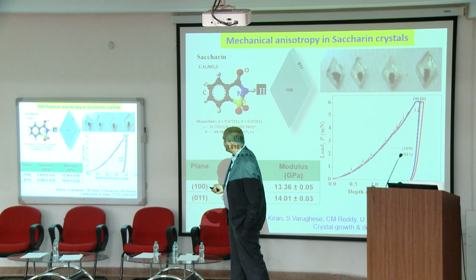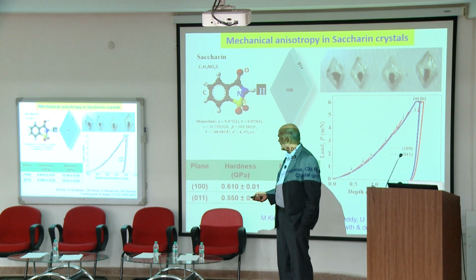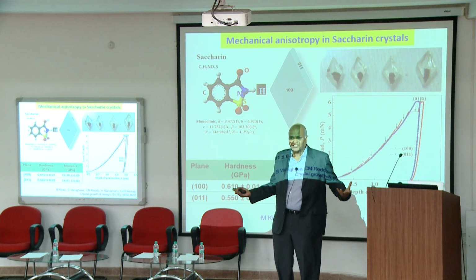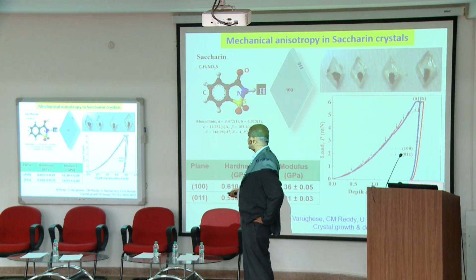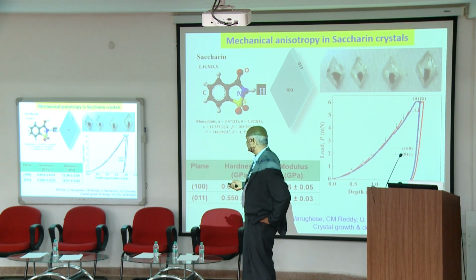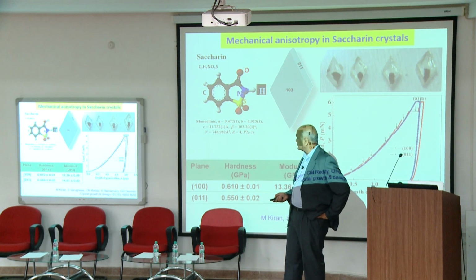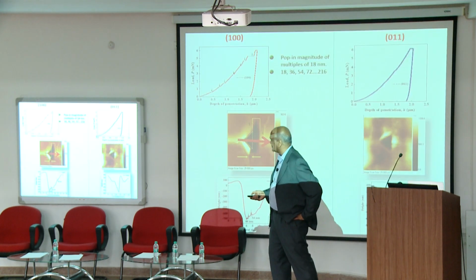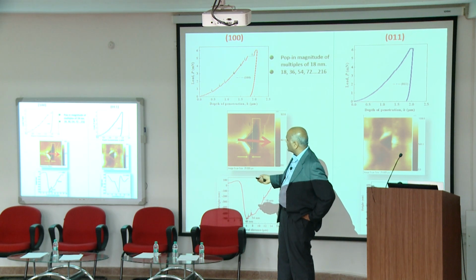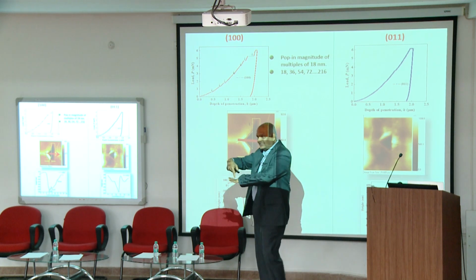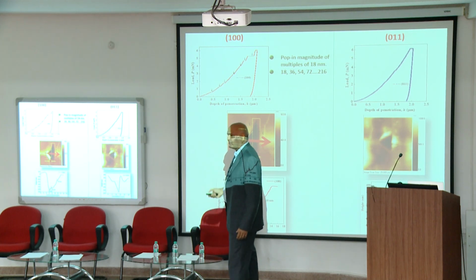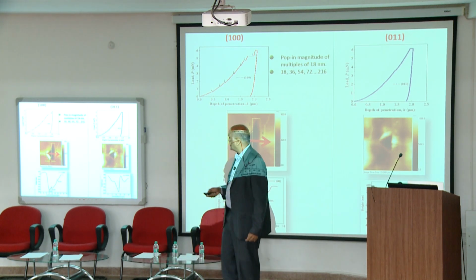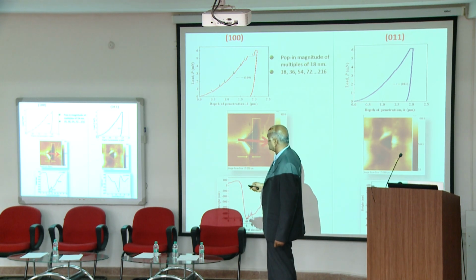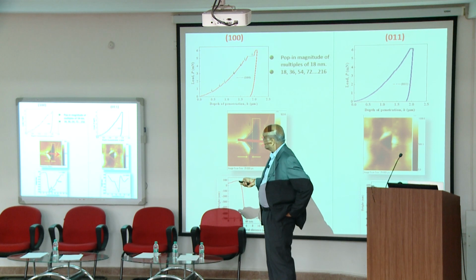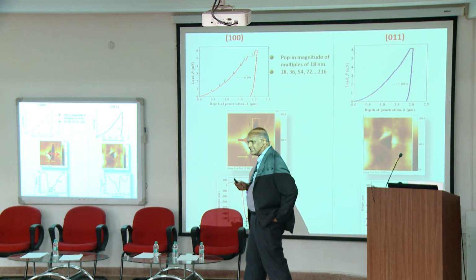So basically we started our first work on saccharin crystals. We took these crystals because they are something we can grow easily and get access to, and we indented on two faces of the crystals, 100 and 011, and we get differences in responses. Let me illustrate. If you look at 011, when I poke the crystal on the 011 face, the response is very smooth, right? The indenter penetrates very smoothly, and then I get the properties. But when I poke the same crystal on the 100 face, I see a lot of these discrete steps.